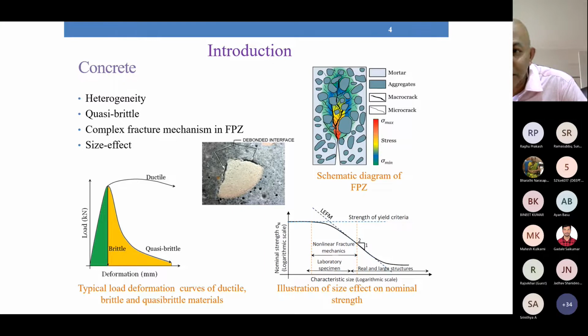So here the size of the process zone is really large, comparable to the crack size or comparable to the size of the ingredients here. So because of the presence of the fracture process zone, we cannot apply the principles of linear elastic fracture mechanics. So some principles of nonlinear fracture mechanics have to be applied. So that constitutes the quasi-brittle material.